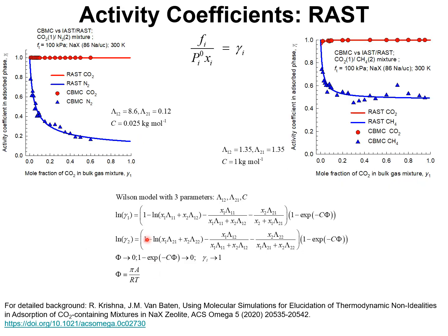The CBMC simulation data could be used to determine the activity coefficients describing deviations from ideality in the adsorbed phase.